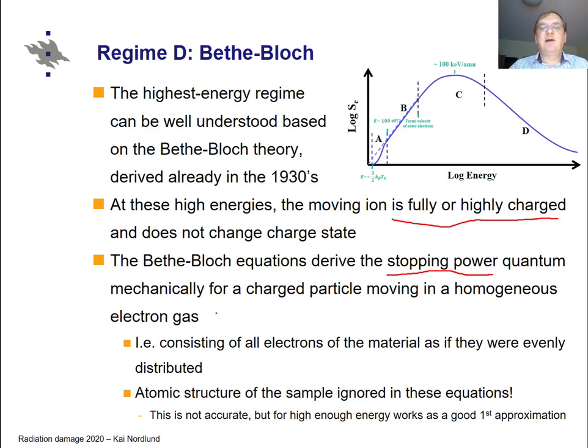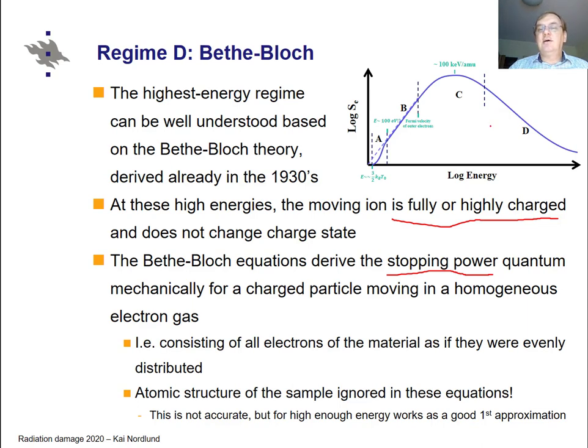This homogeneous electron gas assumption means that the electrons in the material are assumed to have uniform density everywhere. Of course, anyone knowing solid-state physics knows this is not true — the electron density is much higher close to the atomic cores. But if the energy is high enough, the ion moves in a straight path through all the electron densities that exist, and on average the electron density approximates that of a homogeneous electron gas, and it turns out that this average is actually pretty close to correct.